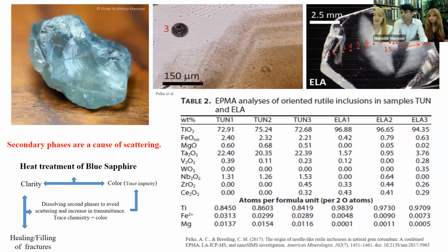So they have found that the majority of these secondary particles are actually titania, which is rutile. It was very interesting because it's highly found in many different mines. Sometimes in some mines, we have a combination of hematite, or maybe hematite and rutile or ilmenite. So it could be a variety of titanium-containing inclusions inside these sapphires that creates these milky appearances and diminishes the clarity very significantly. So we have to get rid of them.